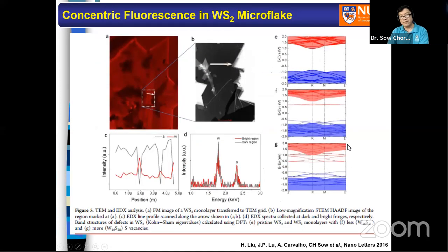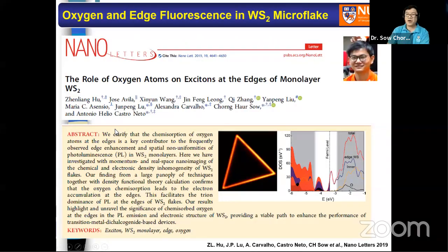Okay, yeah. And then of course, we have help from the DFT calculation to understand what's going on. We do TEM to measure the sulfur content. Indeed, the depletion in sulfur corresponds to the darkness in this particular fluorescence. And there is more to the story, okay? For a long time, we suspected that oxygen must play a role in the behavior of this particular system, okay? So in recent work, Zhenliang Hu used the CVD technique and DFT calculations to prove that indeed, oxygen is the main contributor to the edge fluorescence of the WS2, okay?